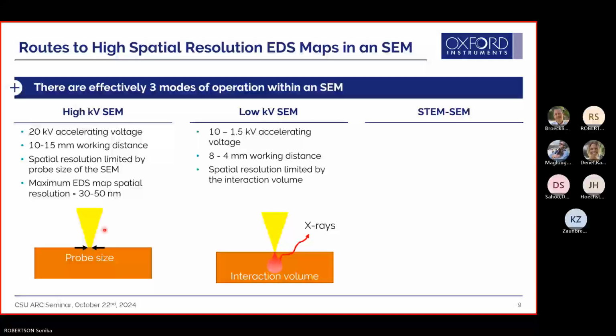The low kV, for us at Oxford, anything below 10 kV we're considering low. Again, it depends on what materials you're characterizing. You talk to nuclear people, they deal with uranium a lot. They wouldn't go below 5 because you're sampling single-digit nanometers, because uranium is so heavy. So low kV, anything down to 1.5 kV. I would have laughed at that 10 years ago. Now it can be done. Your working distance ranges from 8 to 4 millimeters, and your resolution is still limited by interaction volume, but it's smaller than it would be at 20 kV or 15 kV. And you can go down to characterizing 5 nanometer features. I know it sounds crazy. I'll show you some results too.